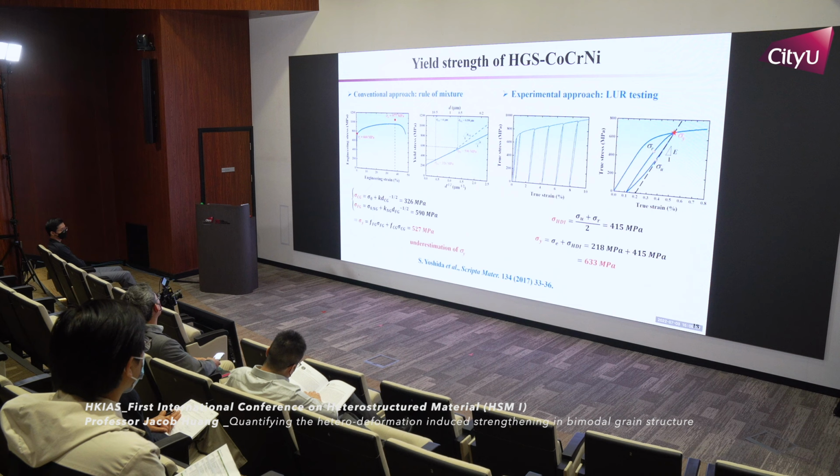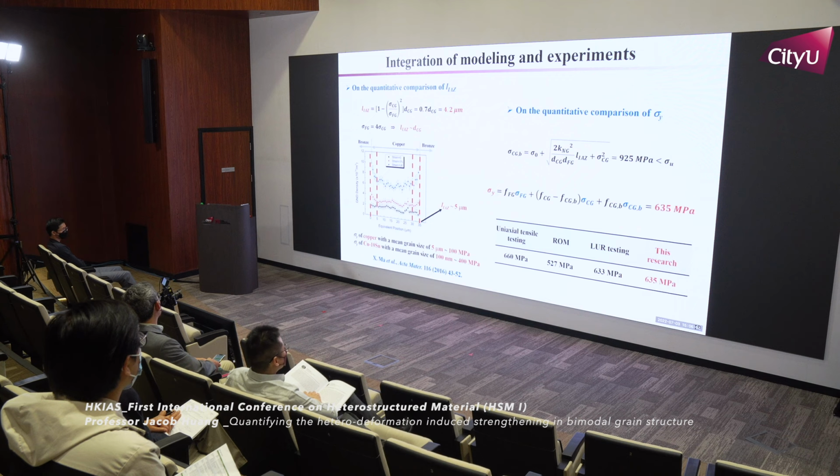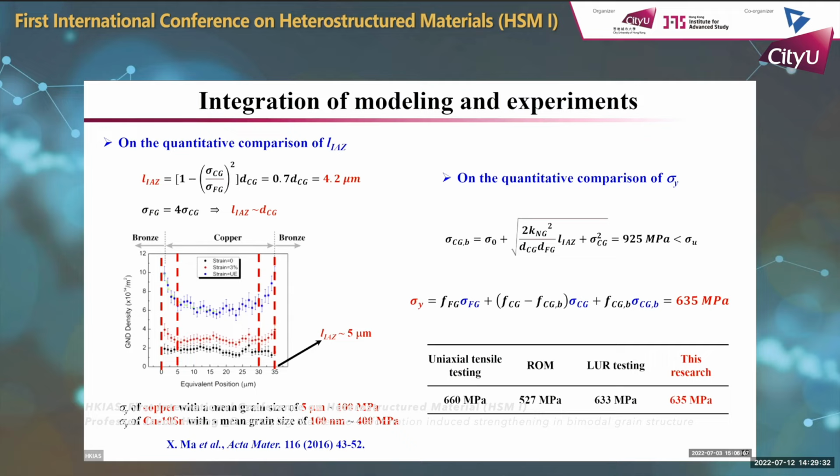Of course, finally, or thirdly, we use our own analytical dislocation model. First, we need to calculate quantitatively the IAZ length by plotting all the parameters. This length is calculated to be 4.2 micron, which is about 70% of the grain size of the coarse grain